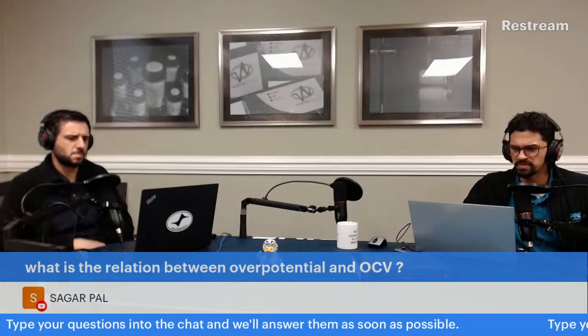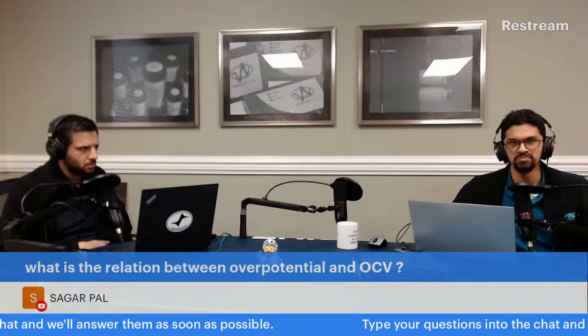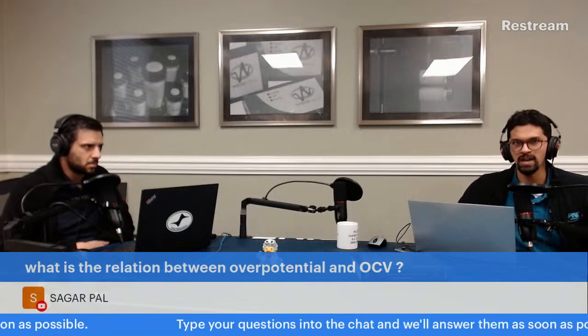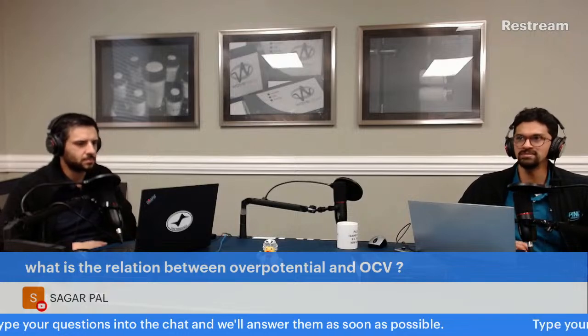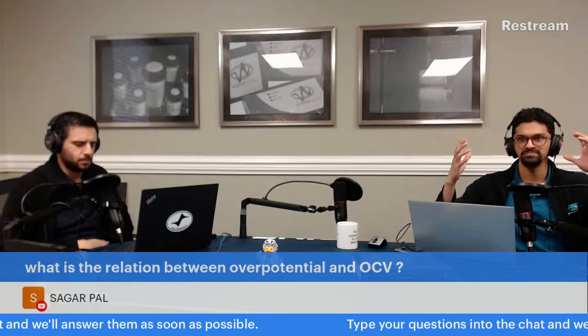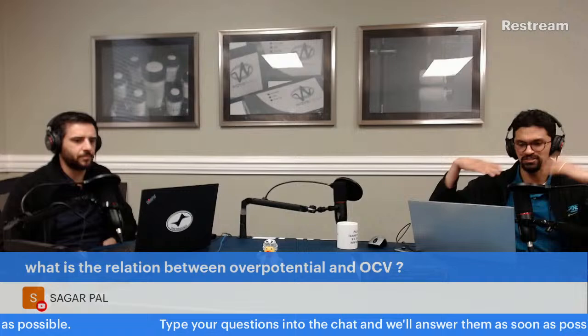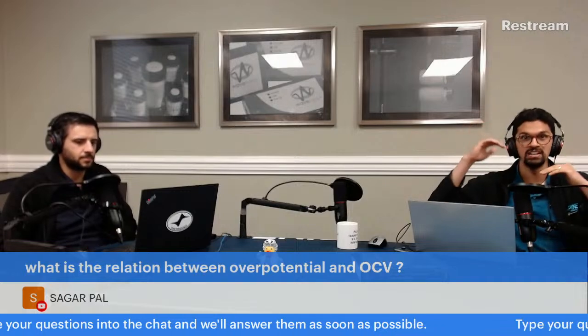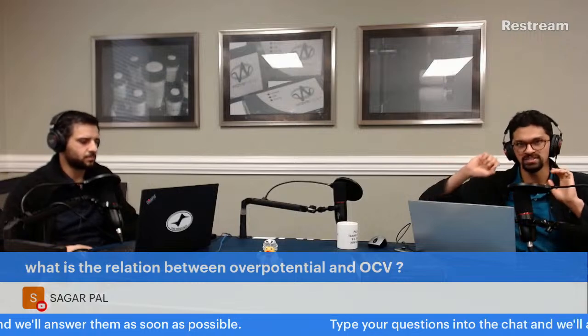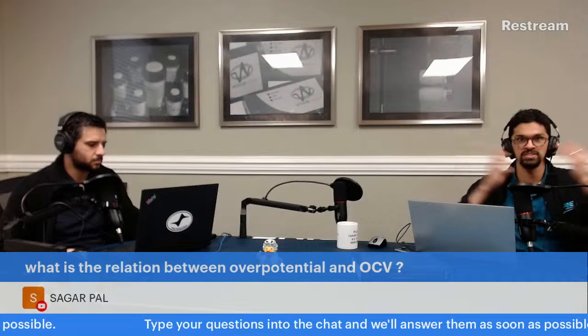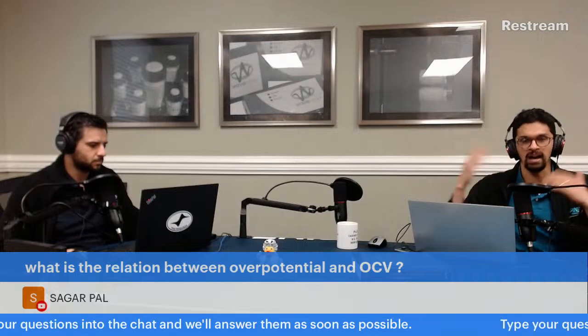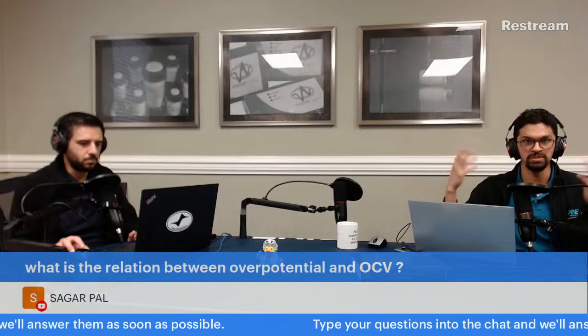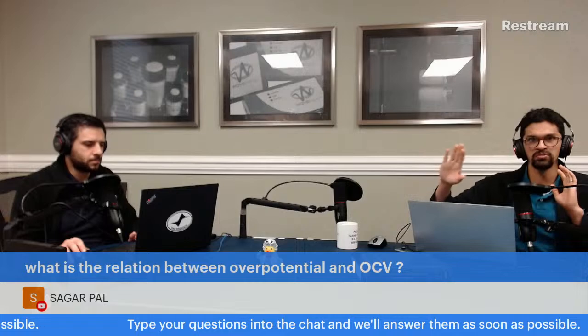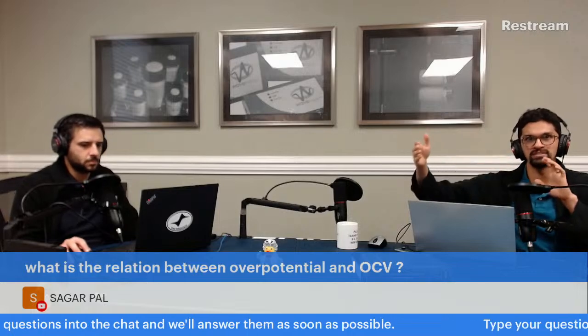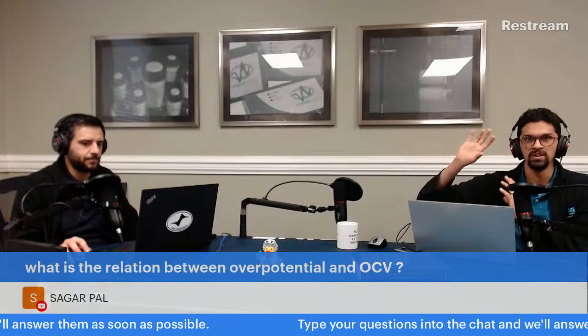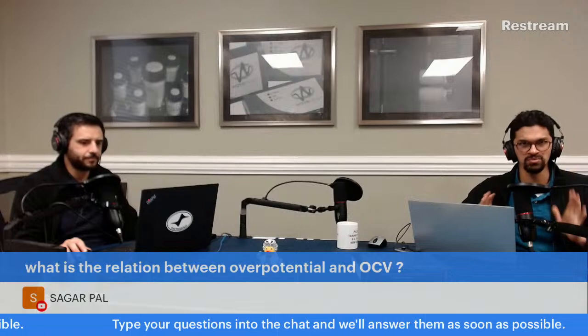Overpotential is the potential beyond the thermodynamic minimum to drive a reaction forward. If you have two species in solution in thermodynamic equilibrium, like in the Nernst equation, and it's 50-50 of both of them, then to drive the reaction in one direction so that you have more of one species versus another, you need extra potential. And when I say species, I mean an oxidized and reduced form of a reversible redox molecule. That's the overpotential. It's the potential to drive it forward, to get current to flow, so you get more of one thing than another.